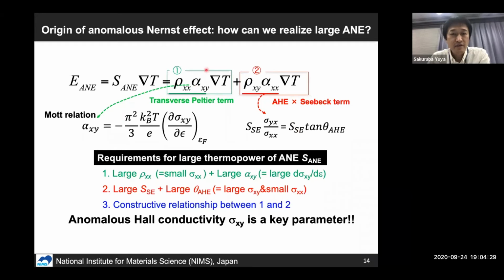And this alpha xy, the off-diagonal part of the thermoelectric tensor, is a very important parameter for the anomalous Nernst effect. And the Mott relation gives this kind of expression: alpha xy is proportional to the energy derivative of the anomalous Hall conductivity at the Fermi level. So the anomalous Hall conductivity is an important parameter for both the first term and second term. Therefore, it is very important to know the anomalous Hall conductivity in magnetic materials to realize a higher anomalous Nernst effect.